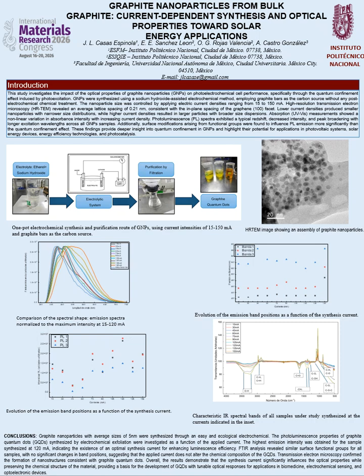Smaller GNPs exhibit stronger quantum confinement, which results in a larger band gap and consequently a higher density of electronic states available for UV-Vis transitions. As the GNPs increase in size, quantum confinement weakens, their band gap decreases, and their electronic structure approaches that of bulk graphite, which has a lower density of states in the energy range of the UV-Vis region. Therefore, the probability of electronic transitions in this spectral range decreases, resulting in lower optical absorption intensity. Simultaneously, the increase in current intensity induced the aggregation of the GNPs, which led to the notable decrease in absorption intensity.